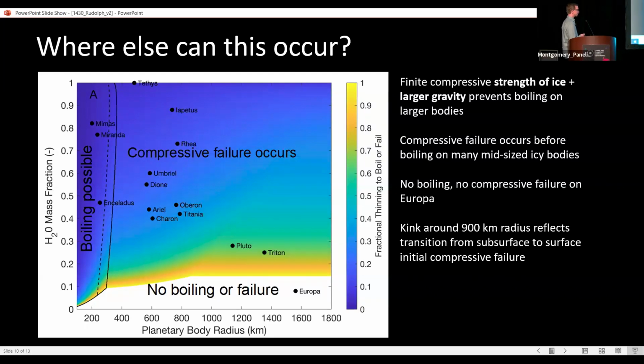This figure is kind of complicated, so I'll take just a minute to explain. The horizontal axis shows planetary body radius. The vertical axis shows the mass fraction of water plus ice in the planetary body. And we've mapped out the conditions under which 3 different things happen. First, for small bodies that plot over on the left side of this diagram, it's possible to achieve boiling conditions within the subsurface. It actually turns out to occur for relatively modest amounts of ice shell thinning. This is possible on Enceladus, Mimas, and Miranda.